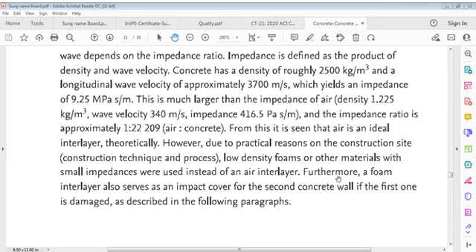Okay, 9.25 MPa. This is much larger than the impedance of air, which has a density of 1.225 kilogram per cubic meter. Wave velocity in air is only 340 meter per second, but the wave velocity in concrete is 3,700 meter per second. If you multiply the product of density, 2500, and wave velocity, 3.7, we get the impedance, much larger than that of air.